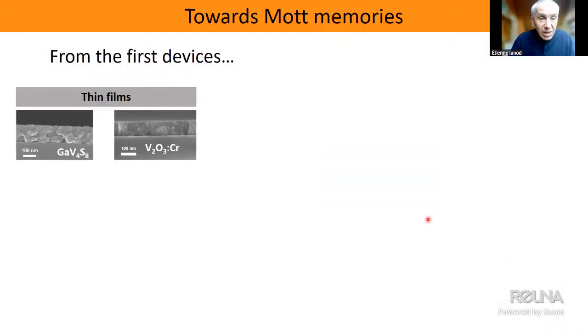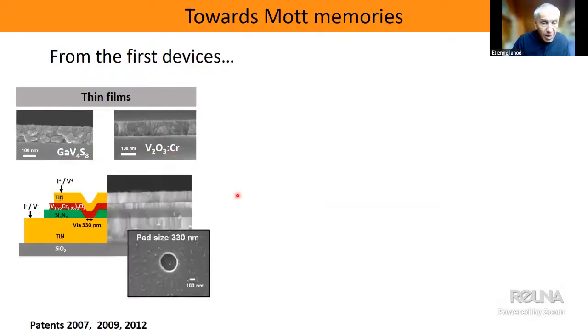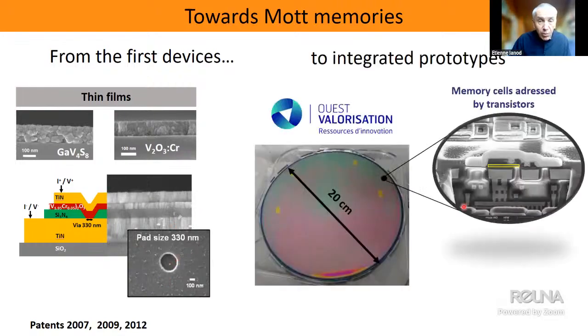So after this proof of principle, we have been able to test different Mott insulators, GaV4S8, the family I already mentioned, and the V2O3 system, V2O3 doped with chromium. Working on such systems, we have been able to go higher in size, and to deposit this layer of material on big wafers, at the level of microelectronics. So you see it's 8 inches, 20 centimeters in diameter, for these wafers.